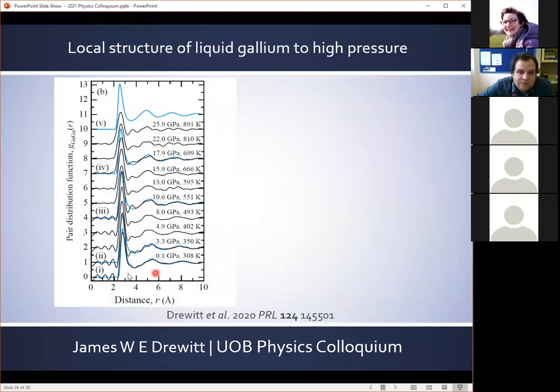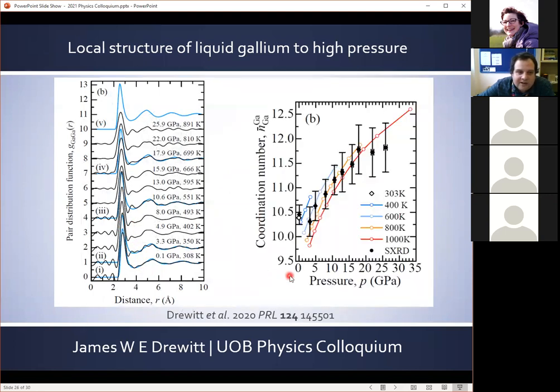So here's the pair distribution functions, and we can integrate over the first peak here to obtain our average gallium-gallium coordination, where the experimental measurements and simulations show a similar trend, where at ambient pressure, the liquid coordination number is around 10, which is lower than the typical value of between 11 and 12, typical of other liquid metals. With increasing pressure and densification, this coordination number increases, approaching a value of around 12, which would be consistent with a simple close-packed structure. But going on this average coordination number alone can be misleading.